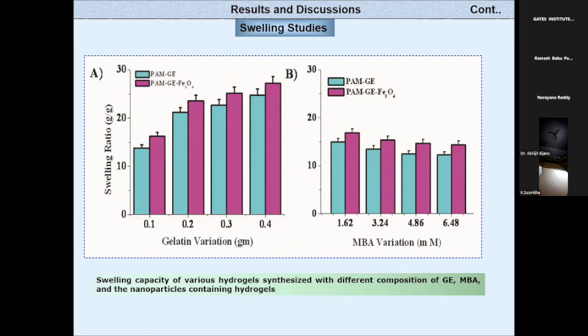But when you are using gelatin, you see an increasing trend. With the MBA variation, MBA is also a cross-linking monomer, which creates big bridges, so the water entrapped should increase. But here we are seeing quite the opposite phenomenon. At a certain molar ratio it is okay, but beyond that it attains the maximum equilibrium stage, so you don't get any further swelling of your hydrogel.